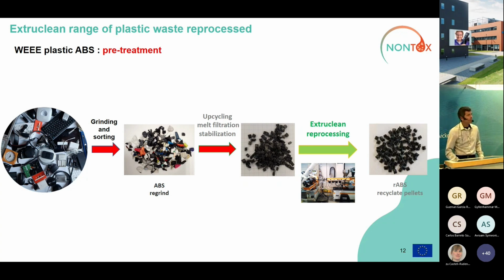So also at the end, we were able to obtain this type of ABS recyclate pellets that were reused for filament extrusion to be used in the 3D printing process. In this case, we take advantage of the low VOC content of these ABS recyclates in order to avoid nozzle clogging in the 3D printers.